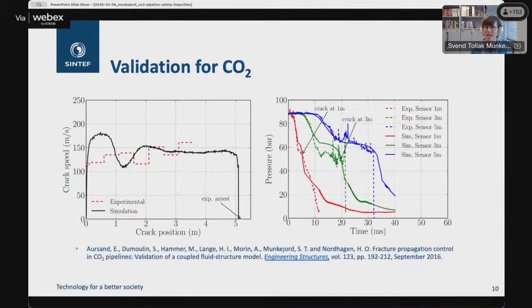But first, some validation we did some years ago for CO2. So I'd like to briefly explain this. The plot at the left shows crack speed plotted as a function of crack position. The red dashed line is the experiment, and the black curve is the simulation. And you can see that the experiment has a slightly coarse resolution. This is because of the way that it's done. You attach strings around the circumference of the pipe, and when they break, you know where the crack is. But at least there is a ballpark agreement here.